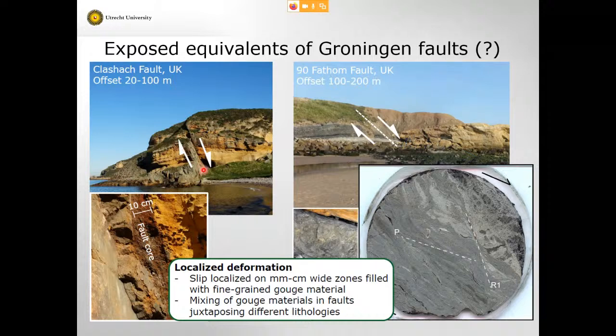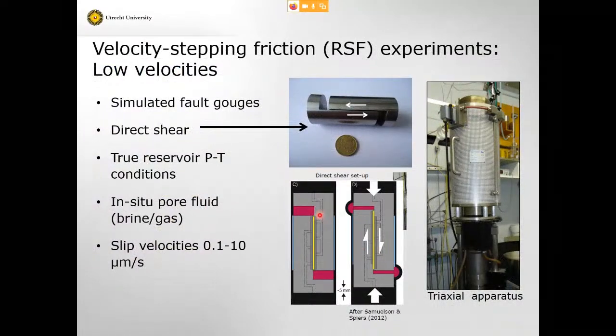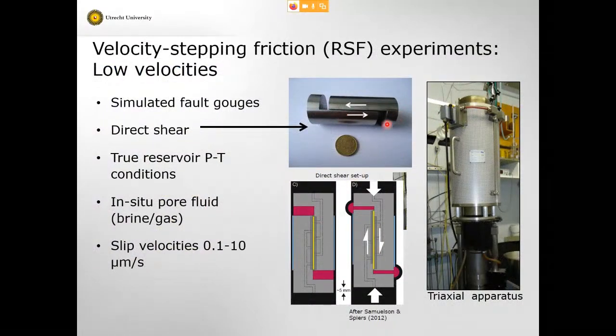The faults themselves are remarkably planar, and most of the displacement is concentrated in very, very narrow slip zones, even far smaller than this 10 centimeter zone in here. Very, very narrow zones and discontinuities within the core of the fault. So that gives us a little bit of confidence that direct shear friction experiments on thin layers of crushed up fault material, fault gouge, in a triaxial machine under in situ conditions would give us a sensible way of quantifying the frictional properties of these fault rocks, the rocks that would be found in these faults in the field.